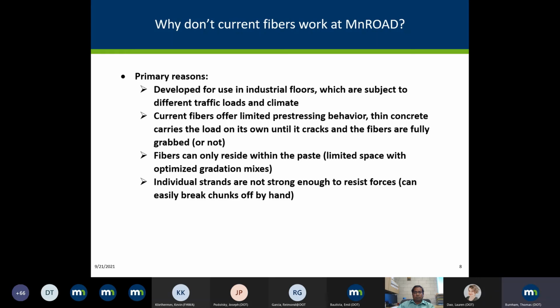The fibers can really only reside within the paste. So we also have this issue that we have very optimized gradation mixes, we want less shrinkage, we have less paste. Well, the paste is the only place that you can put a fiber. So perhaps there has to be some changes in the type of mixtures that we make. And as I showed before, the individual strands themselves are not strong enough to resist the forces. So again, perhaps the fibers that we have been using so far, we need to look for something more robust, down to even the individual fiber itself.